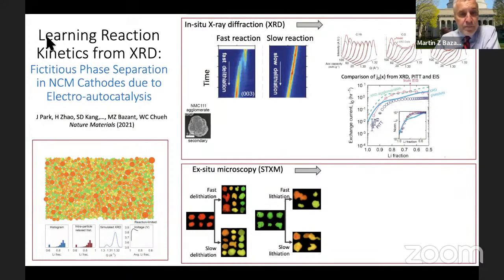And what's interesting is that if you look at these pictures in the middle, the vertical axis is time, the horizontal axis is the wave number of a certain X-ray diffraction peak. If you slowly delithiate, going downward here, you see that that peak moves smoothly, and there's only one peak. That corresponds to the lattice slowly expanding or contracting at low rates as lithium is taken out. Now, if you take out lithium quickly though, at a certain time there's a breaking up of those peaks, and it looks like there's phase coexistence, as people had observed before.